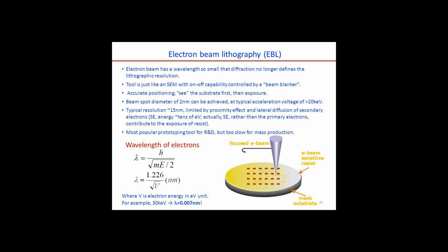This point is driven home by the 2007 demonstration of double patterning using electron beam lithography in the fabrication of 15 nanometers half-pitch zone plates. Although a 15 nanometers feature was resolved, a 30 nanometers pitch was still difficult to do, due to secondary electrons scattering from the adjacent feature. The use of double patterning allowed the spacing between features to be wide enough for the secondary electron scattering to be significantly reduced. The forward scattering can be decreased by using higher energy electrons, a thinner resist,